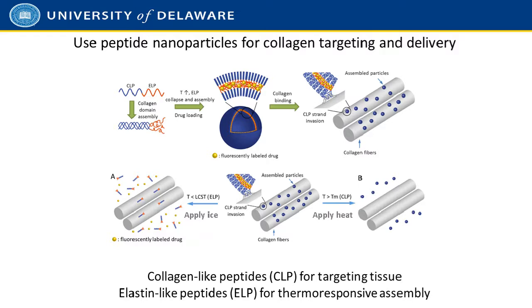the bottom center of the image, that nanoparticle could either be dissolved by lowering the temperature, if one could apply ice, or by heating the temperature, that collagen triple helix can be unfolded, and then those particles could come off the collagen or be dissolved altogether. So this is a two-component system where we use the collagen-like peptides for targeting tissue and the elastin-like peptides as a way to make these collagen-targeting nanoparticles responsive to temperature.